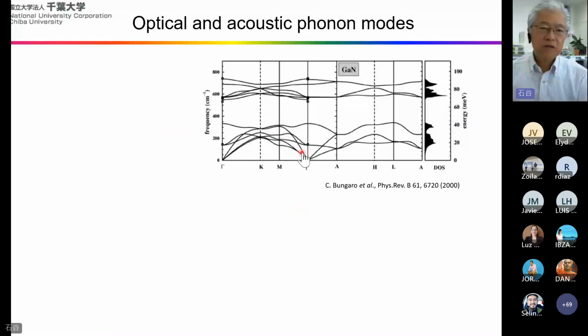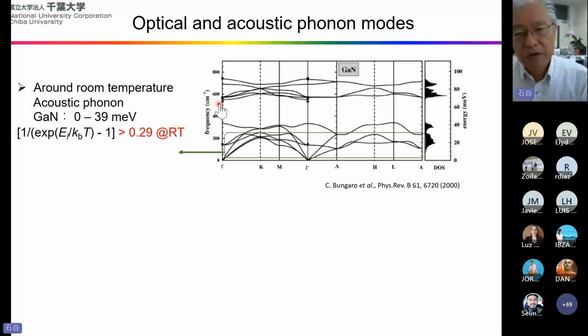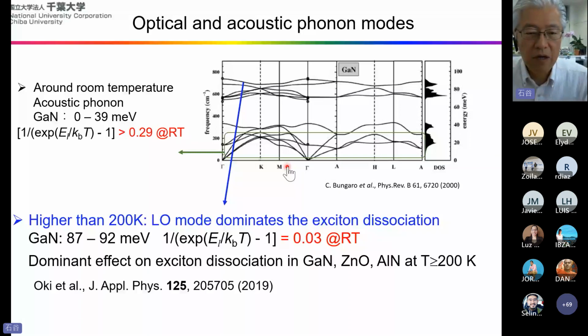So this is a dispersion curve of phonon energy. The abscissa is the momentum of phonons, and the ordinate is the phonon energy. When we usually use the word heat energy, these low energy acoustic phonons are considered. People are now focusing on these phonons, but in FETs, lasers and LEDs, the most toxic phonons are the longitudinal optical phonons. Optical phonons produce the most severe problem.